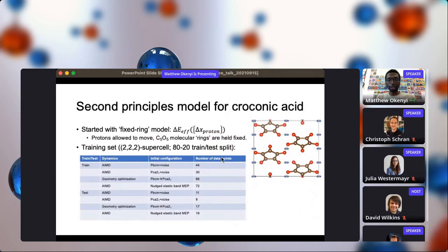So the pool of terms which capture all carbon, oxygen, and hydrogen atom displacements, consistent with a maximum order of terms of 4 and a spatial cutoff of 11 Bohr, which is the width of one of these molecular rings in croconic acid, gives a pool of terms which has a size on the order of 100,000, and so this makes training quite expensive and time-consuming.